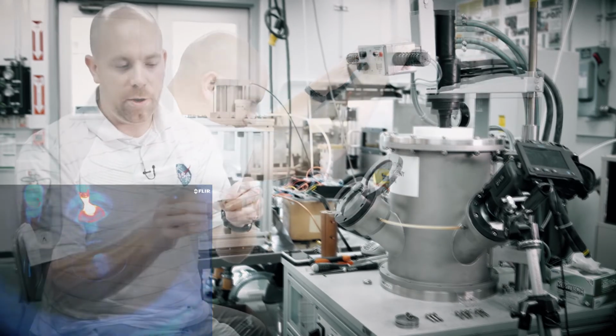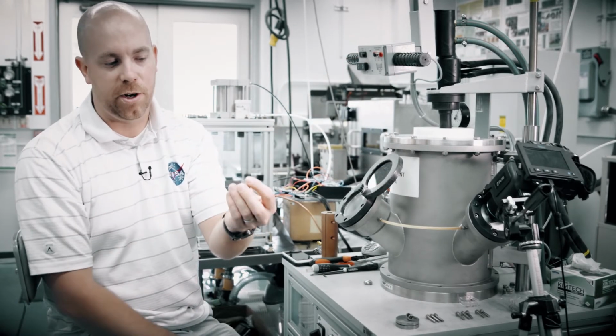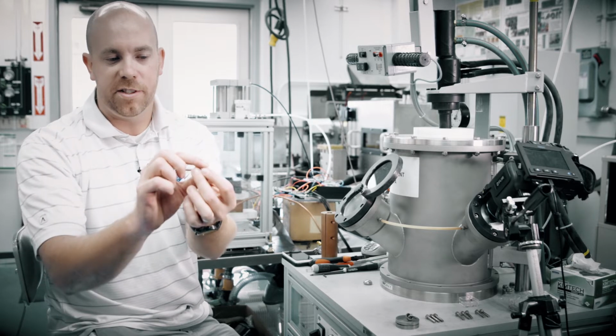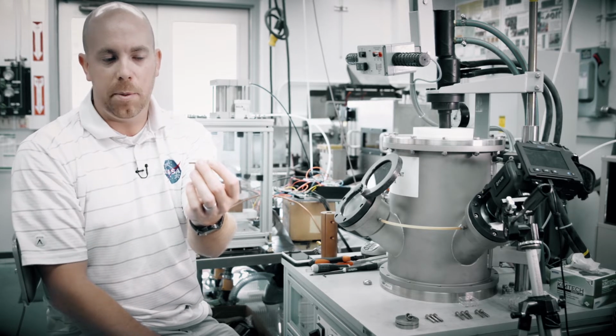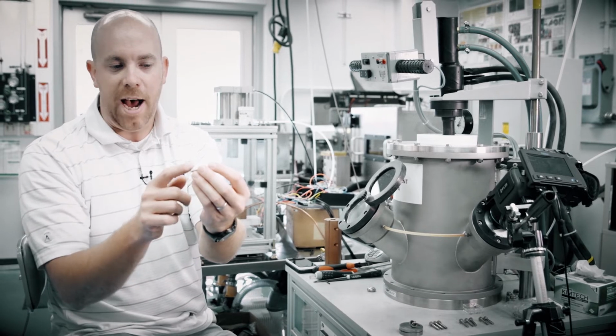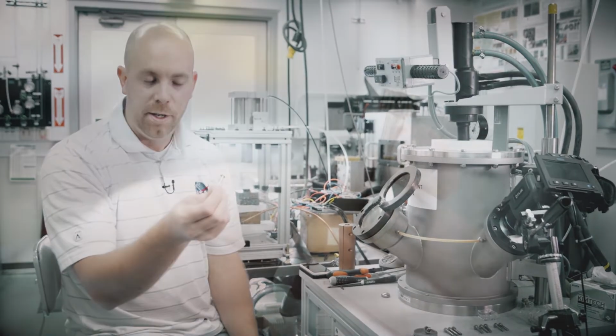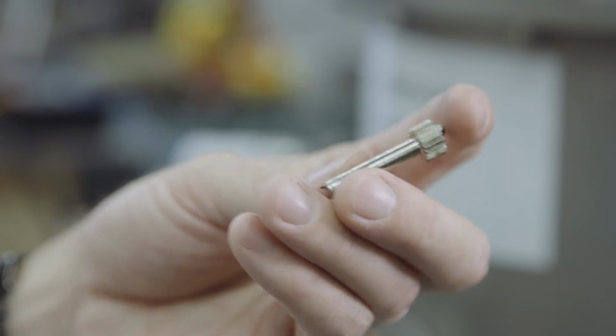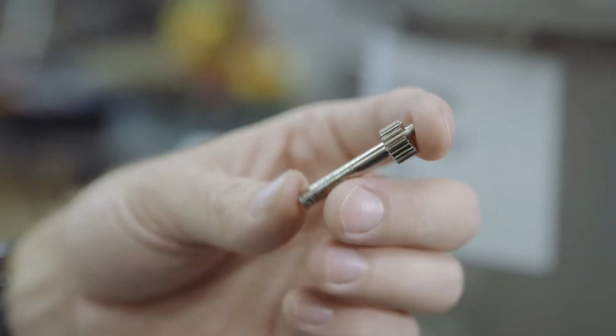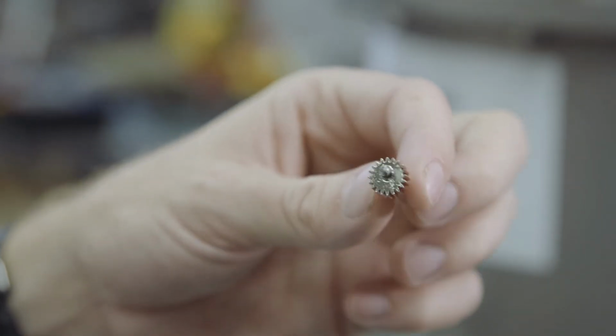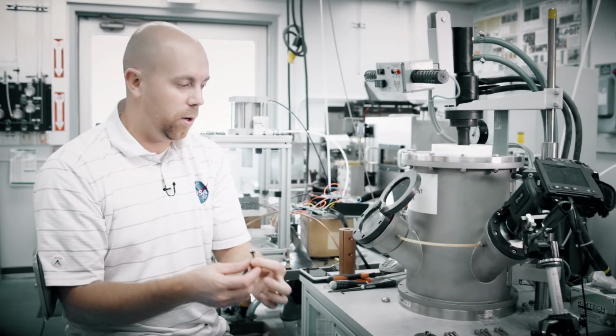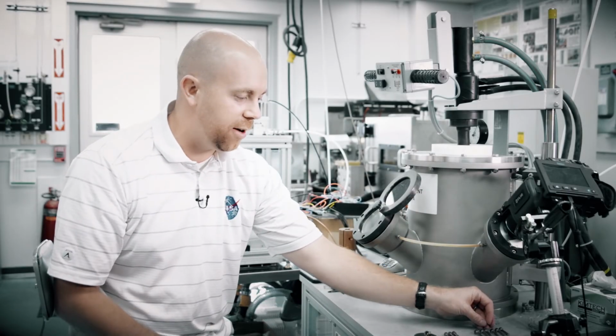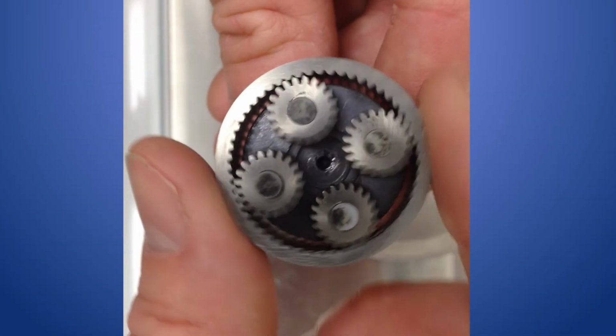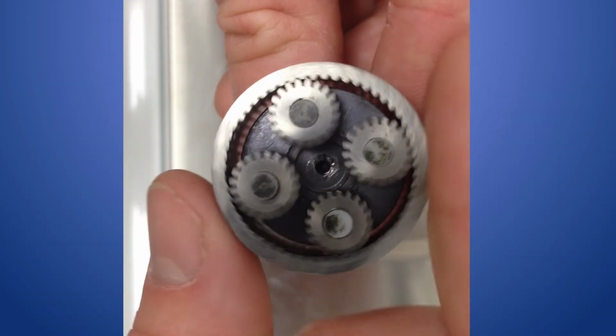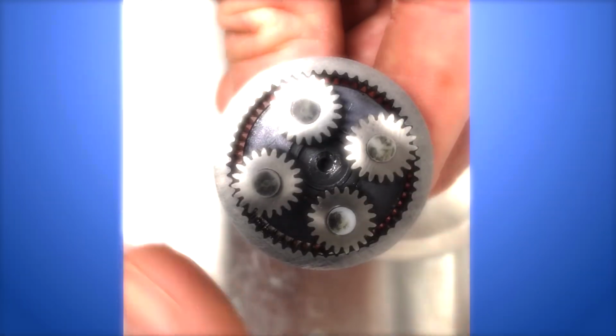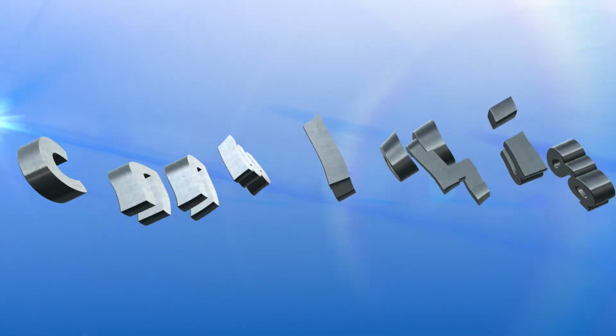And there it goes. Compared to the way that these gears are manufactured in industry, this has to start as a billet of steel that's this big, and it has to be machined into the shape of the shaft, and then the teeth have to be hobbed, which is a technique that's used for making gears. With metallic glass, we can actually cast these in one single step into a mold that's reusable, so that we can make thousands of gears out of one single mold. And yet we get wear properties that are superior to steel from the metallic glass gear.